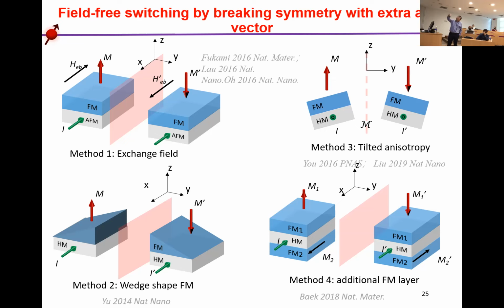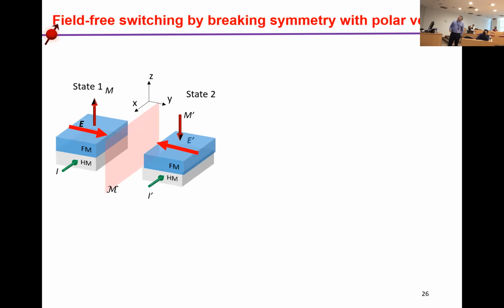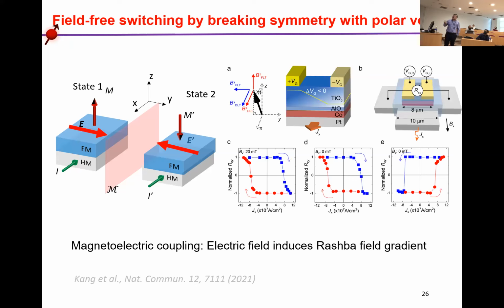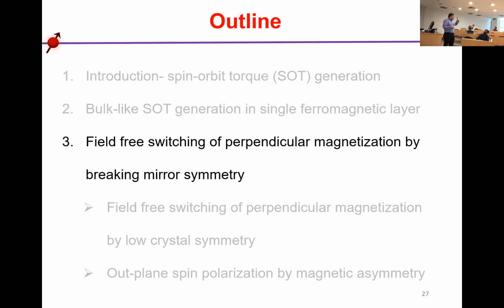But from here we can say we control the axial vectors. But we can also use a polar vector to break the mirror symmetry. For example, now the polar vector must be perpendicular to the mirror plane. So this also has been demonstrated. When you apply an electric field perpendicular to the mirror plane, we can cause field-free switching. But all this is by controlling the polar vector or axial vectors. Now we use some low crystal symmetry to break the mirror symmetry and induce field-free switching.